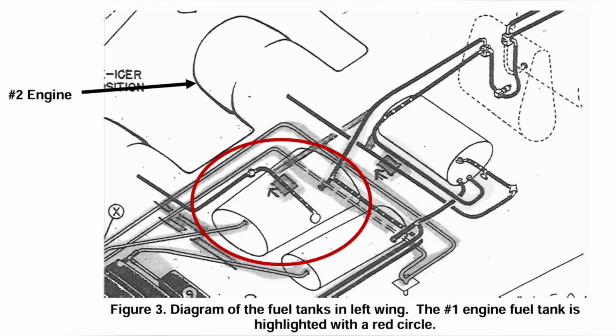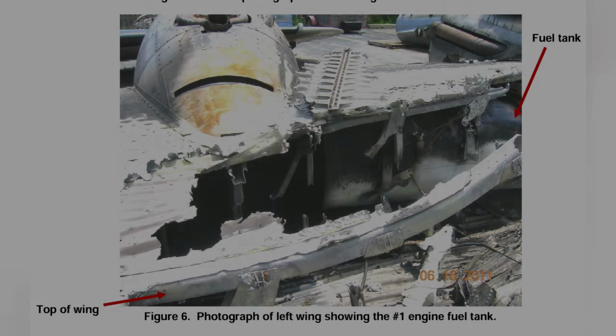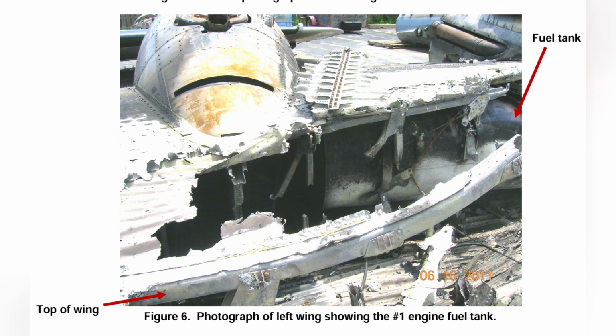During post-accident examination, the tank was filled with a small amount of water, and droplets leaked from the aft repair area near bolt number 2 and the partially separated channel. The aluminum C channel was then removed, and the repaired region of the tank was saw-cut for closer microscope examination. This shifted the investigation from a broad wreckage survey to a targeted materials analysis of the exact fuel containment boundary that had failed. The critical hardware recovery was not a dense alloy artifact sifted from a slag pool.